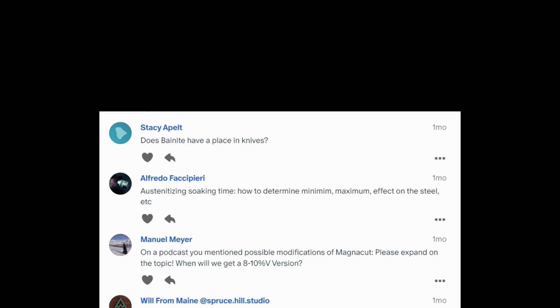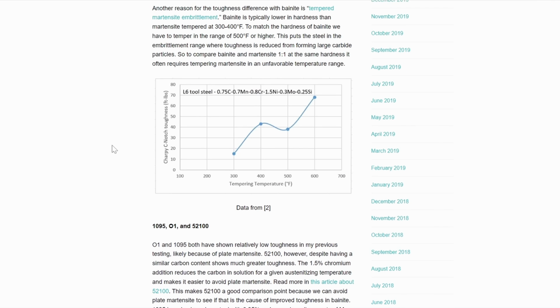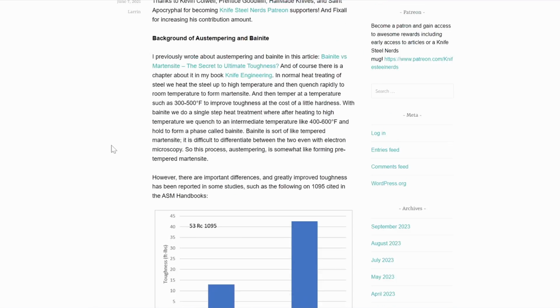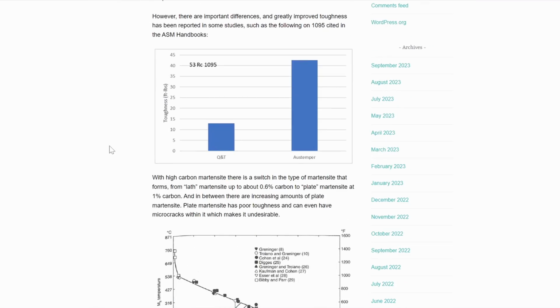Stacy asks, does bainite have a place in knives? So I have talked about bainite before. What is bainite? Do I have a good chart here? Well, to talk about the potential benefits of bainite, this is quench and tempered, meaning normal martensite, you heat it up hot, you quench it in oil, then you temper it at a low temperature versus an Austemper. And this old chart shown in a bunch of old handbooks that I recreated here, 53 Rockwell C1095, the Austempered, that means bainite, was way tougher than the quench and tempered.